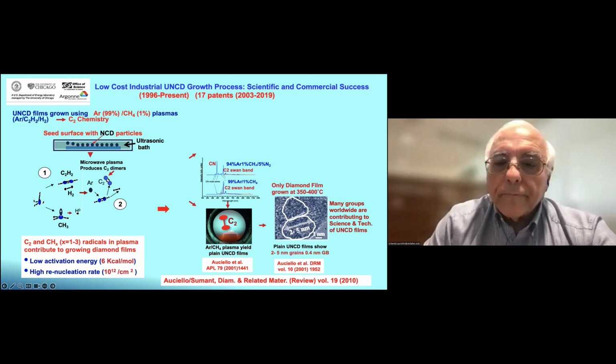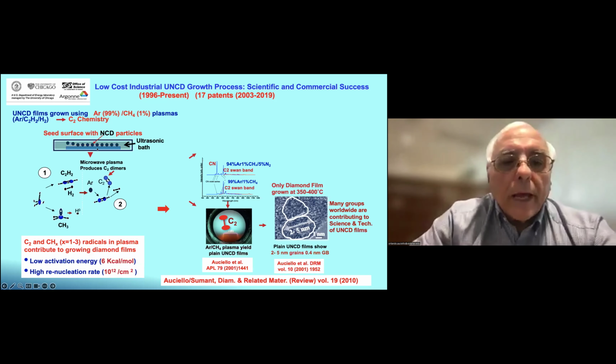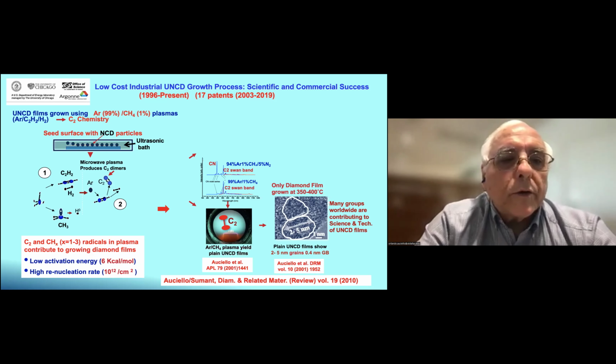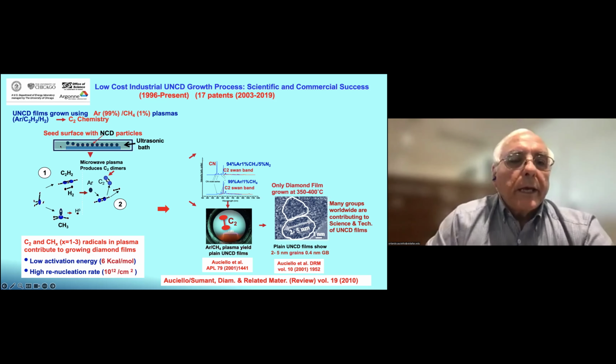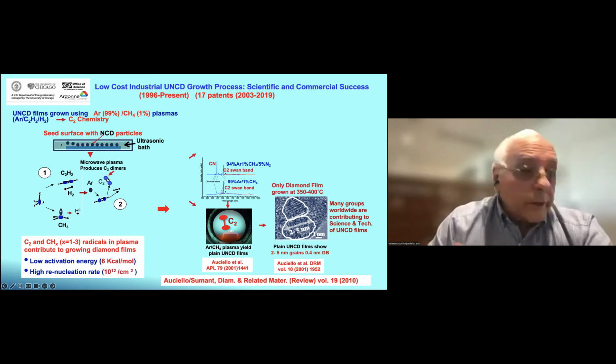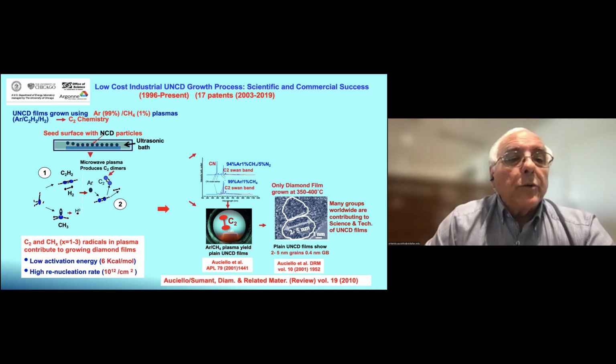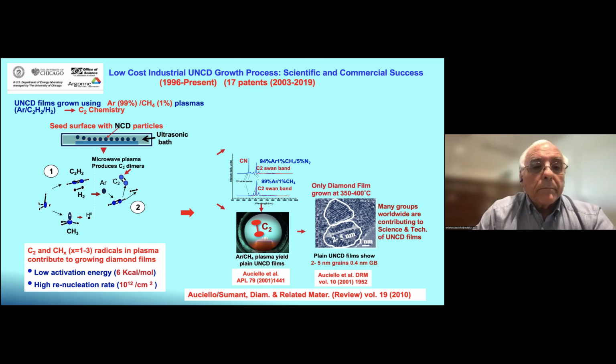So then we decided to do more fundamental and applied science, computer simulations, experiments, and we found that if we replace the 99% hydrogen by 99% argon, we were able to grow the same film. Now, everybody growing these films does what is called the seeding process, where you put the substrate in an ultrasonicator now mainly, with a solution of nanocrystalline diamond particles in methanol. The sound waves shake the particles embedded on the surface, and those are the so-called seeds, simulating the seeds that you put in the ground.